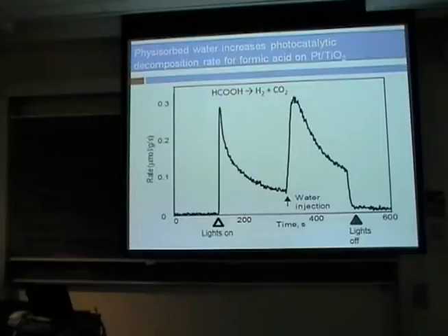And so one interesting thing that we see that is sort of an echo of electrocatalysis is that the presence of a solvent really affects the way the reaction proceeds. Right? This is obviously going to be important when you have a photoelectrochemical cell for water splitting: you're going to have solvent there, you're going to have water, and you're going to want to dissociate that water. And water really affects the way that these organic compounds, for example, react.